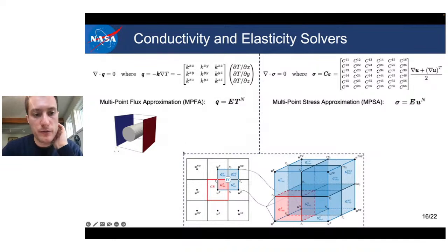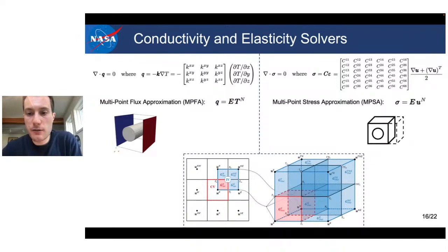But at a high level, what we're solving for is a boundary value problem, where we are imposing a temperature gradient for the conductivity by holding two surfaces across a domain. In this case, I just have a cylinder, which could be a fiber, if you will. By holding these two surfaces at different temperatures, you create this temperature gradient. Similarly, for the elasticity, we are holding a displacement. We're imposing a unit displacement in the 3 Cartesian directions.